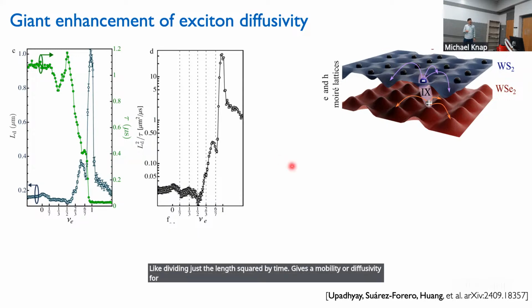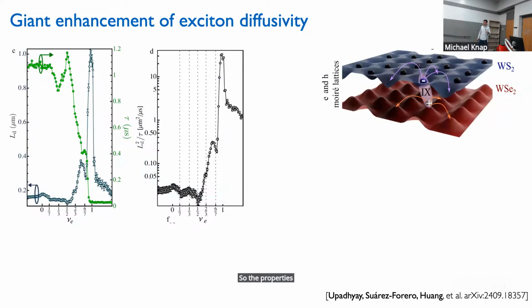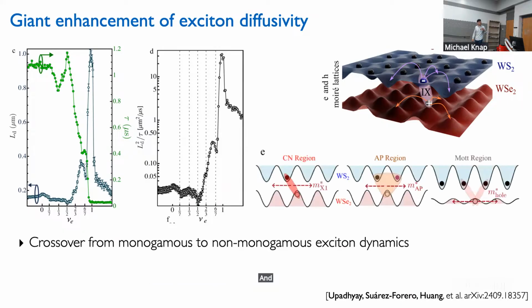And you see gigantic variations of this quantity as a function of the filling. In particular, this is logarithmically scaled here. There's a three orders of magnitude increase of the diffusivity in the vicinity of the Mott insulator. So the properties of the exciton are strongly influenced by the presence of these correlated states. And this is what we wanted to understand.